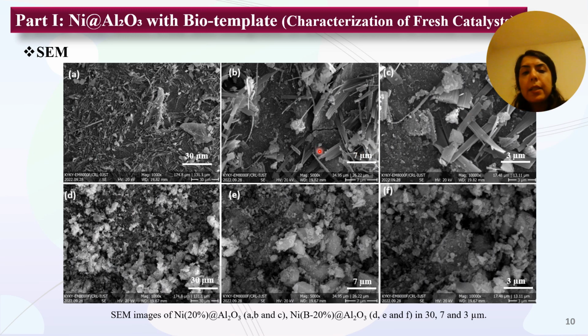Here are the SEM images of nickel-based alumina in the presence and absence of biotemplate. The SEM images A, B, C are related to the sample without biotemplate, and you can see that the catalyst had a tight and needle structure. But when we added the biotemplate, we had a spherical and porous structure.